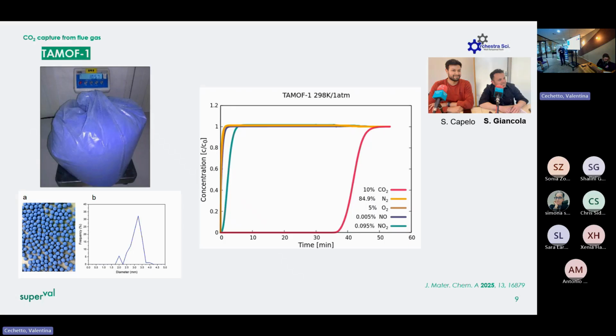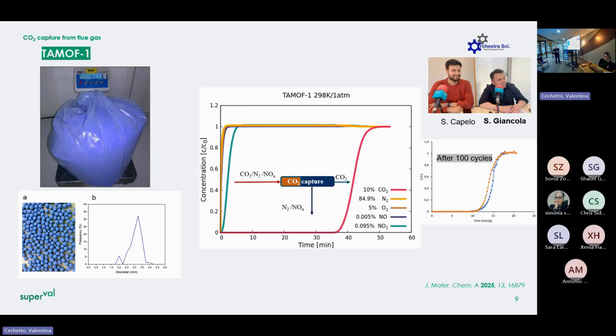This is a breakthrough curve in a synthetic mixture mimicking flue gas. All other components of flue gas exit the bed very fast, and then you can get CO2 accumulated, and then extract it with a very high purity from flue gas, 10% CO2 in this case, to 99.9% in just one step. So this is how this material is solved.